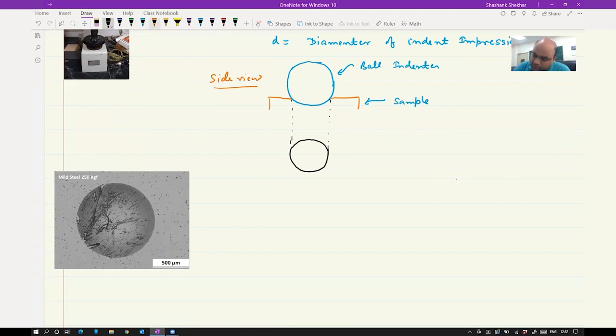Okay, so what we do, we measure D1 and then along the other direction, perpendicular direction, we measure D2. Okay, so we measure two diameters, D1 and D2. So here D1, D2 are diameters. Okay, so diameter of the indent impression when you see from the top, and you take the average. So this will be average of D1, D2.